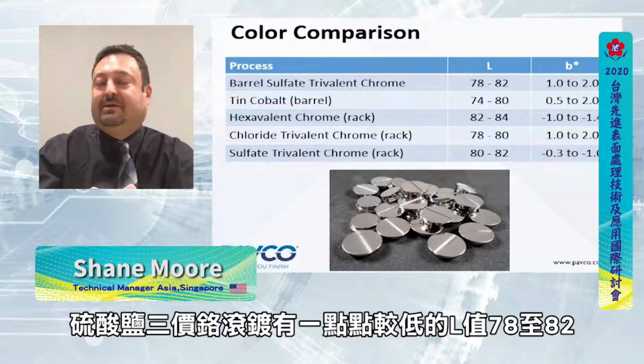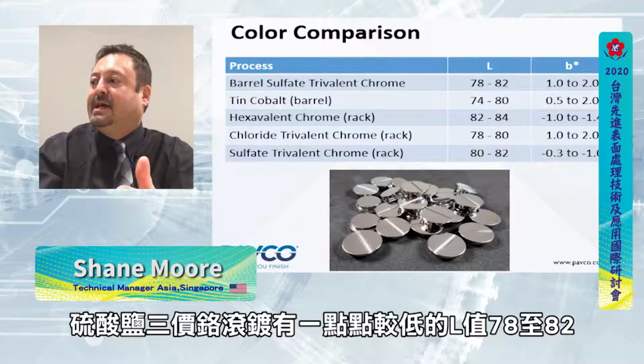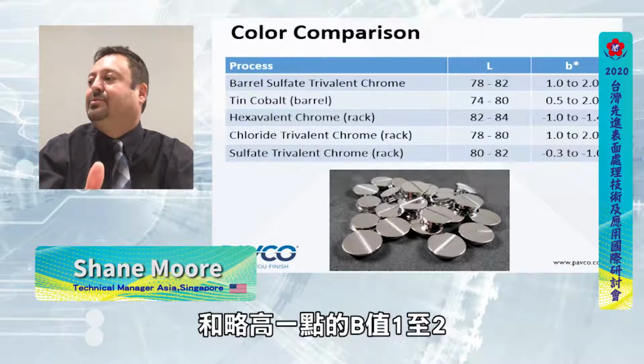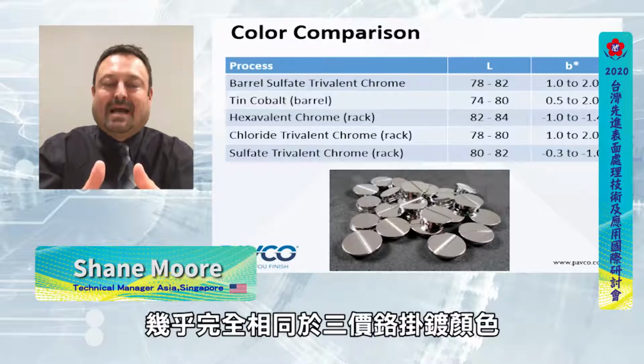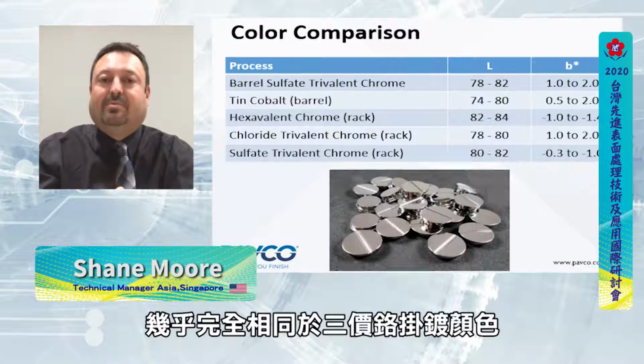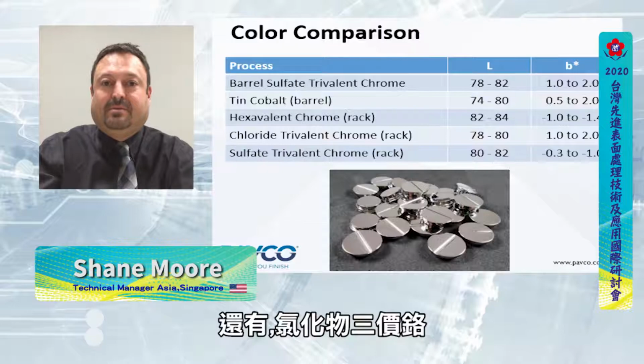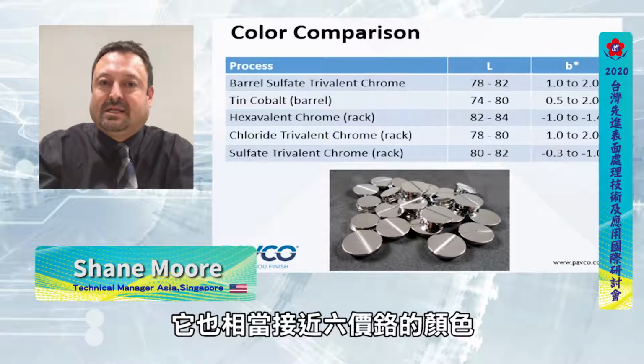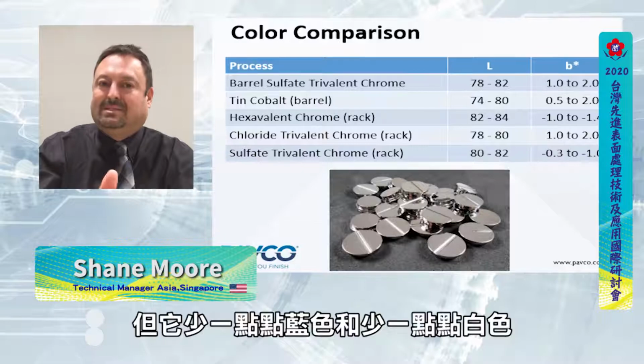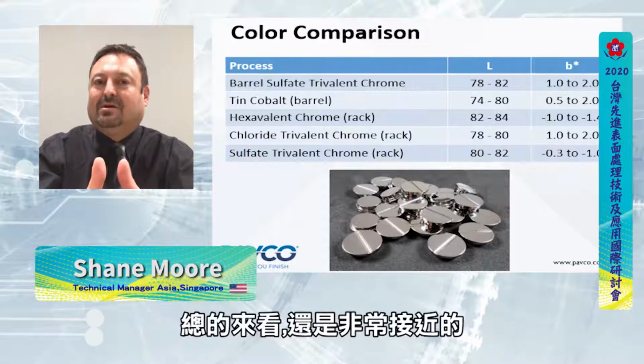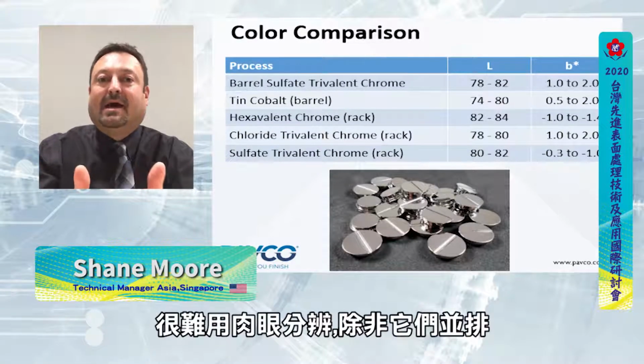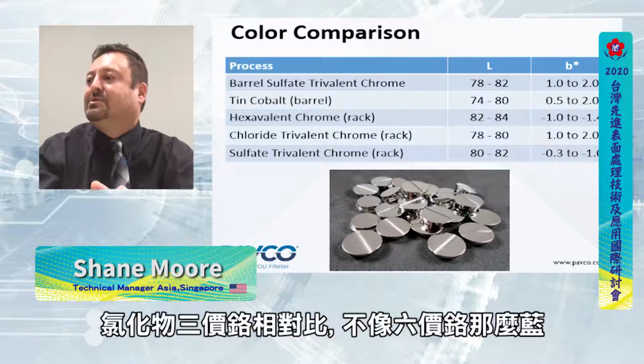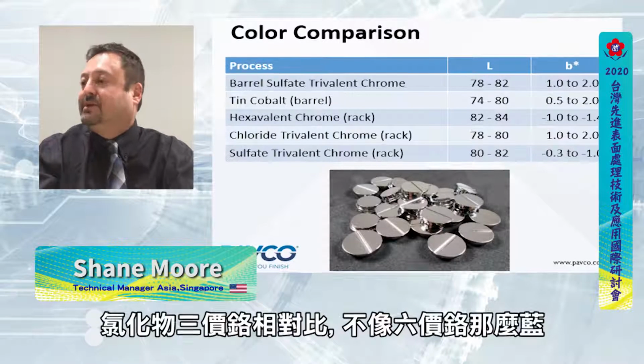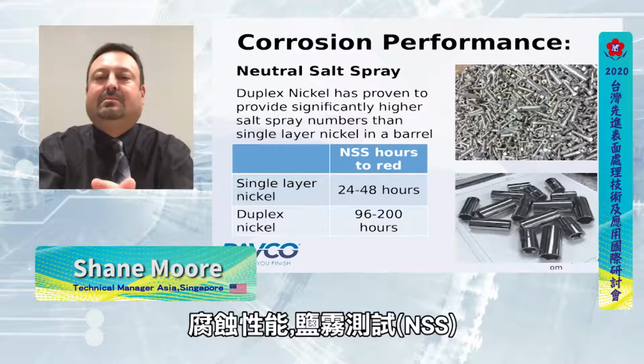The barrel sulfate trivalent chromium has a little lower L value, 78 to 82, and a little higher B value, 1 to 2, but it's almost the exact same color that you get with a hexavalent chromium deposit. Chloride-based trivalent chromium is also pretty close to hexavalent chromium color, but it's not quite as blue, not quite as white. It's very close. It's almost hard to tell by the naked eye unless they're side by side. So it's going to be the darkest and not quite as blue as the hexavalent chromium. The corrosion performance, neutral salt spray.